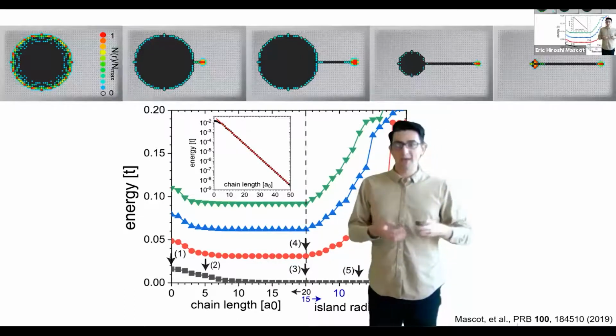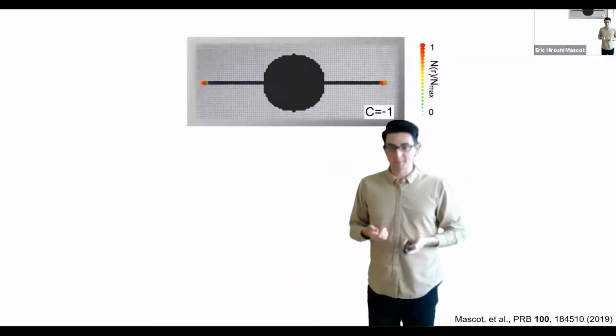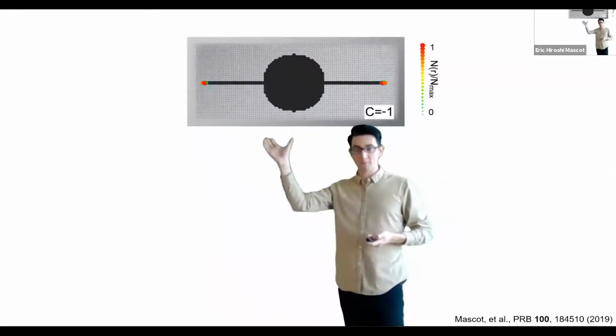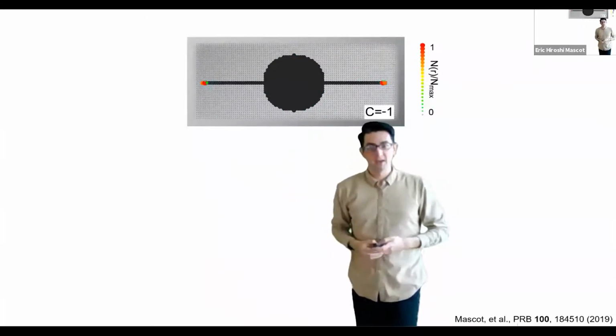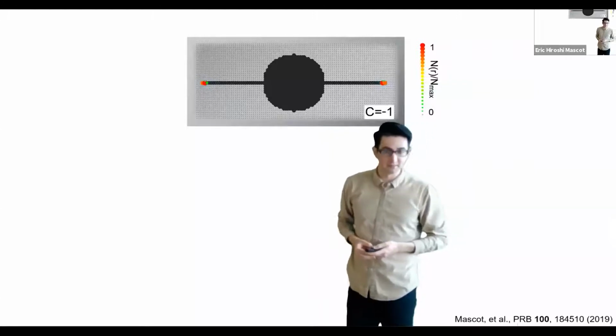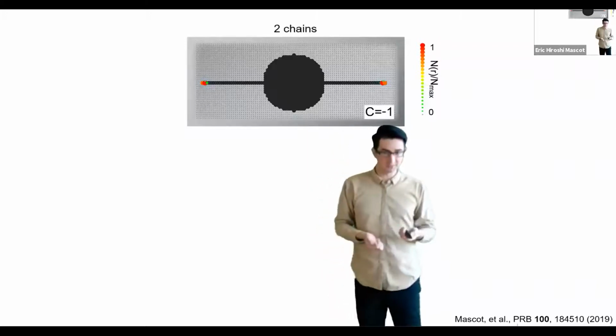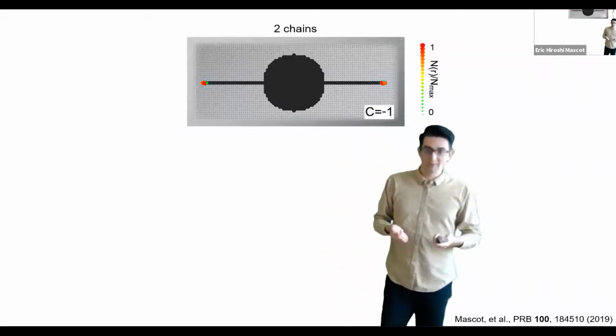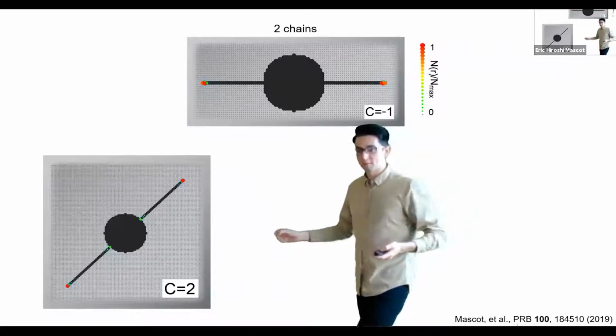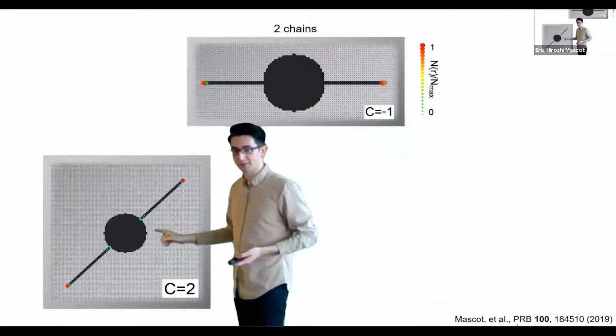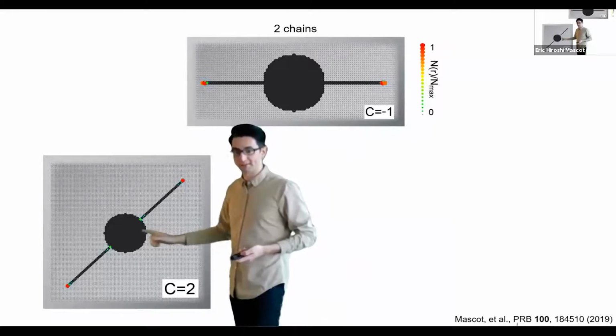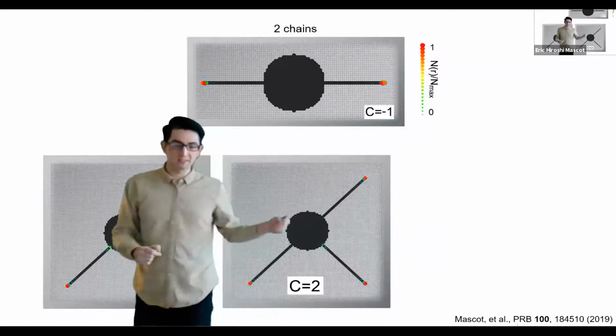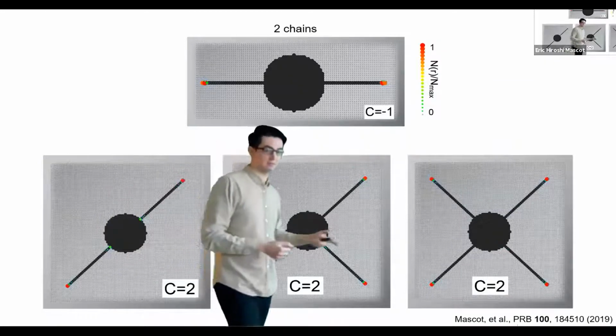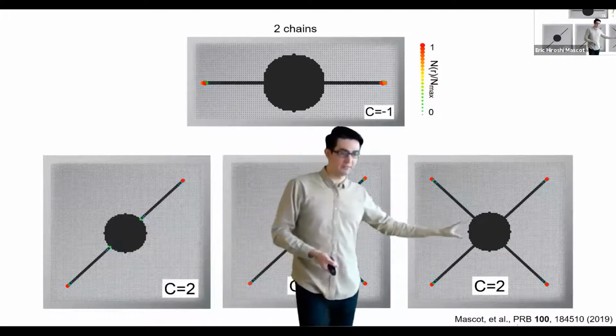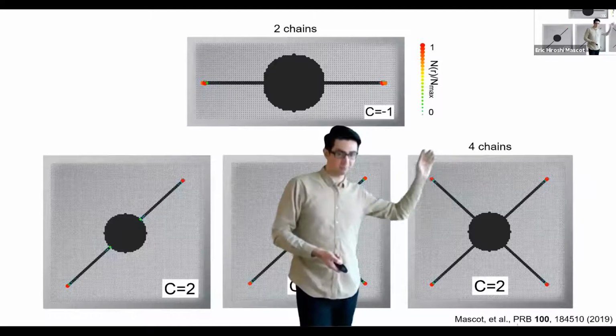So what happens if we add an additional chain? Now we lost any signature of the edge mode inside the island. And all that remains is the Majorana bound state. And that was with two chains. But in the C=2 phase, we do have some signature where the chain connects to the island. And so if we continue adding chains, eventually we pull out any signature from the edge of the island. And this time it was for 4 chains.